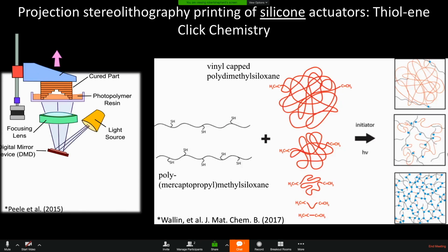We used a Carbon M1 stereolithography printer using an elastomeric polyurethane to make those prior demonstrations. There's also a silicone polyurethane available for that system, but none of them are as soft as we would like. They're all 500 kilopascals and up, and a lot of the projects we work on, we want to use for biomedical devices that can be used in the body for surgery potentially. And so for that, we want sub 100 kilopascal elastic moduli so that we stay below the threshold of damage for a lot of our sensitive internal organs.